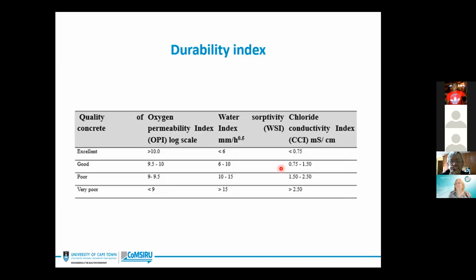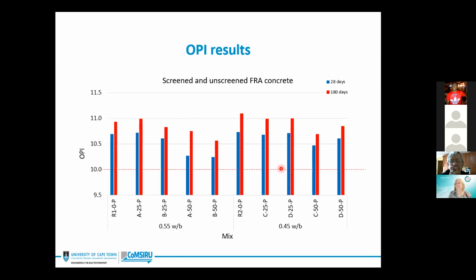For durability properties, we shall use the 3DI test as we have mentioned a while ago, the OPI, CCI, and WSI. As a guide, here are some values that give an indication of concrete quality for these tests. Now, the OPI values for all the concrete mixes are above 10. So this indicates that the concrete is of excellent quality on the basis of OPI. We can see that the OPI values reduce as FRA content increases. You can see that trend. This indicates that porosity and penetrability of concrete reduces with increasing FRA content.